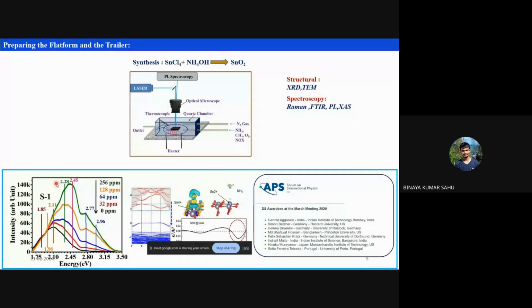Those who don't know about the PL, just think this is some random line. And those who know about the PL, I'll give a brief idea of what is happening here. This is the PL spectra, a luminescence spectra from the tin oxide, and this is pretty much clear. But when you give different concentrations of ammonia, like 32, 64, 128, and 256, you can see there are certain changes in this region, especially 2.77 and 2.96 eV. If you convert them to wavelength scale, they come in the blue region. So in the presence of ammonia, there is an increment in the PL spectra in the blue region. Okay, so that is the trailer. Then we'll see how all the things are happening.